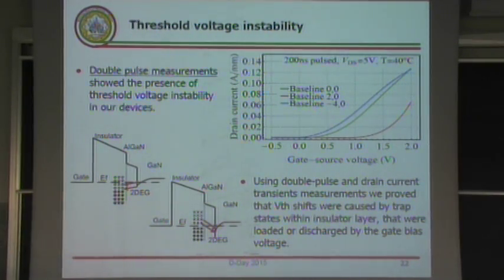However, we see that using double pulse measurement, that is a setup we developed during my PhD, and basically allowed us to measure the dynamic characteristic of the device starting from different bias conditions, we see that effectively the device has a normally off operation. You can see that the threshold is just some hundred of millivolts above 0, but it is still a normally off device. However, it presented many threshold voltage shifts caused by the change in the gate bias point.